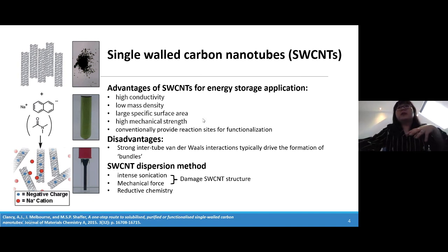However, the problem with this material is that its nature has high pi-pi interactions, or strong intrinsic van der Waals forces, that can cause restacking and also make the single-wall carbon nanotubes bundle to each other, which leads to a lower specific surface area and causes poorer electrochemical performance afterwards. To disperse the single-wall carbon nanotubes in solution, normally in industry, they use intense sonication or mechanical force. But these two methods can actually damage the structures of the SWNTs, create defects, and then lower the specific surface area and give poorer conductivity.